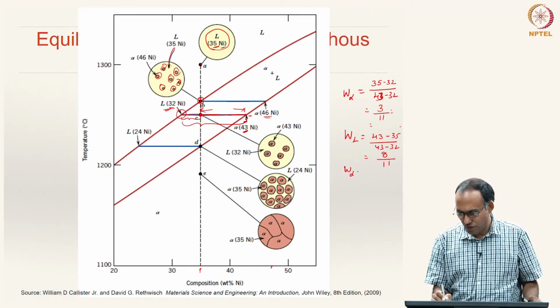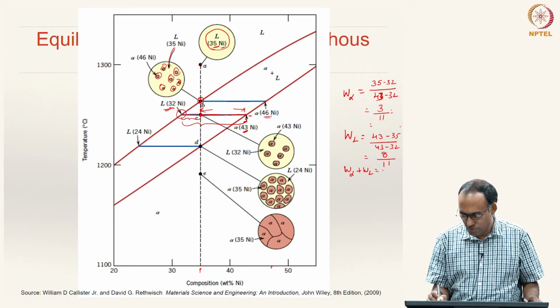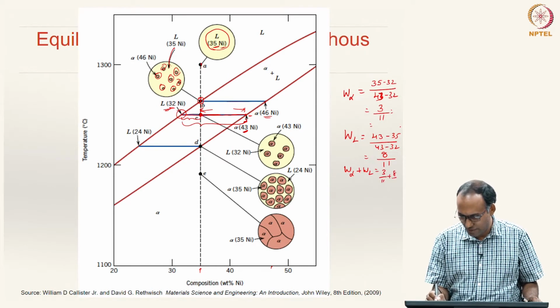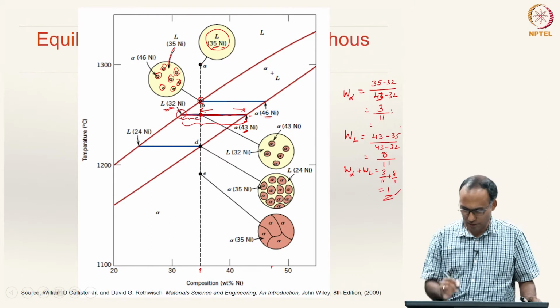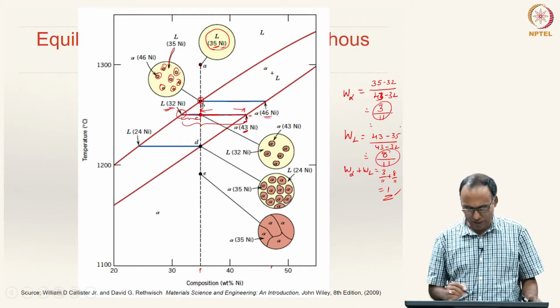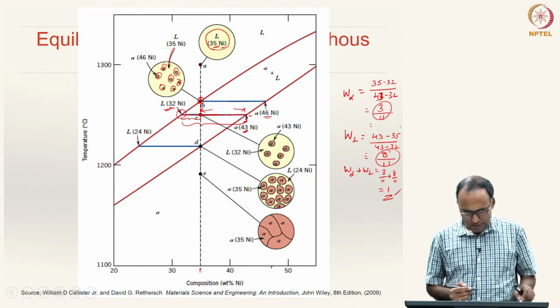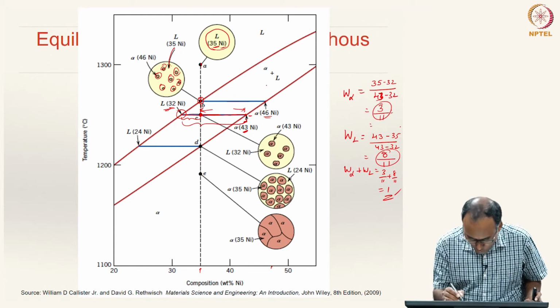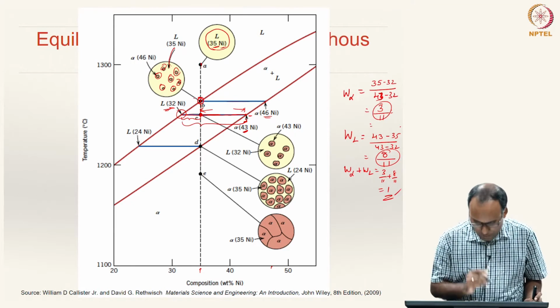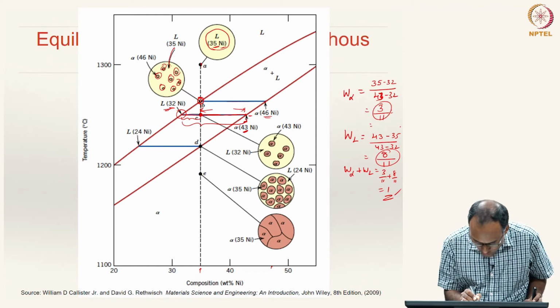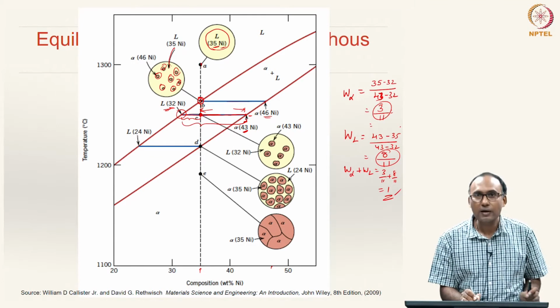So, we should always have W L plus W alpha must be equal to 3 by 11 plus 8 by 11, that must be equal to 1. So, it is working. So, this is 3 by 11, this is 8 by 11, that is the weight fractions. So, you can see now if you look at position B, the distance from the fulcrum point to the liquidus is 0.